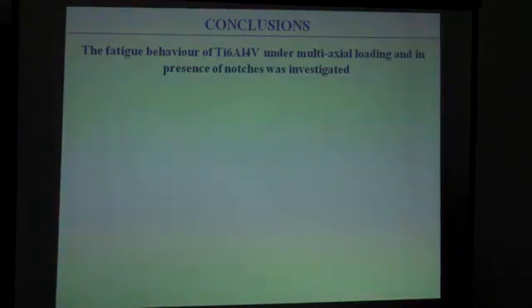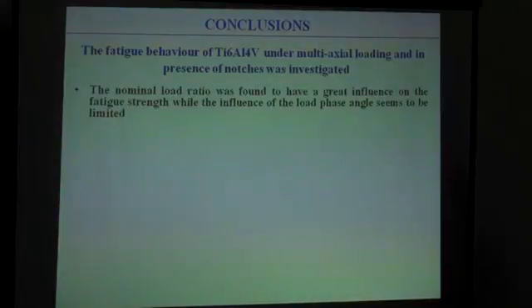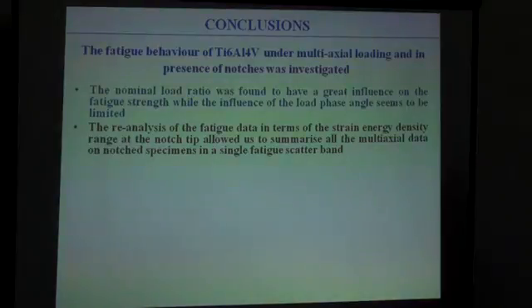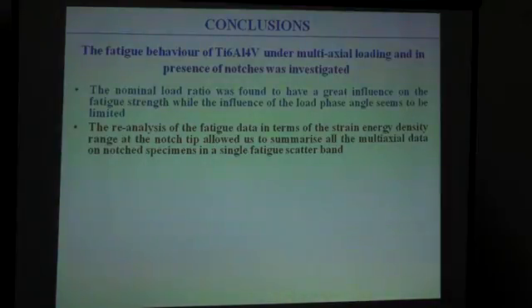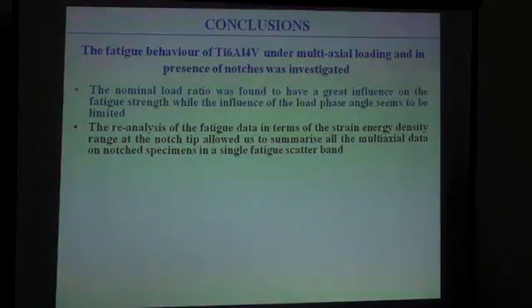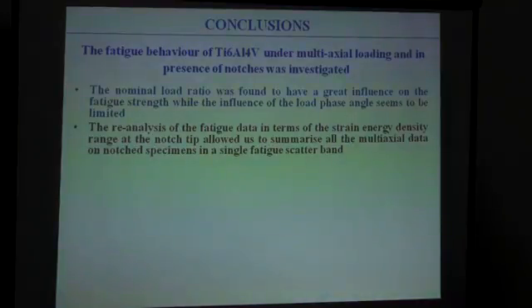In conclusion, I have to say that we have considered different combinations of load for titanium alloys. The nominal load ratio was found to have a great influence on the fatigue strength, and the effect of phase angle seems to be very limited. The reanalysis of the fatigue data in terms of the strain energy density range at the notch tip allowed us to summarize the data inside the scatter band. We have a problem with the definition of the control volume. If we consider the linear elastic hypothesis, we have two different control radii for tension and for torsion. This is a possible problem.